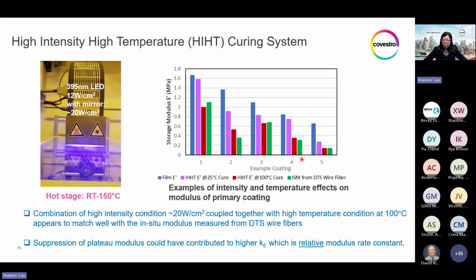And this chart with 5 example coatings, all showing the same effect, that the film modulus with this high intensity device, but set at 25 degrees C temperature, purple bars, is lower than the typical conveyor system modulus, the blue bars on the left. And then when the temperature rises to 100 degrees C, it further drops to the red bars. And the modulus level in these red bars in all these 5 examples is now closely matching the modulus on fiber, which are the green bars. So we assume this suppression of the plateau modulus on fiber, caused by the high intensity and high temperature, could very well have contributed to the higher Ke, because Ke is the relative modulus buildup rate constant.